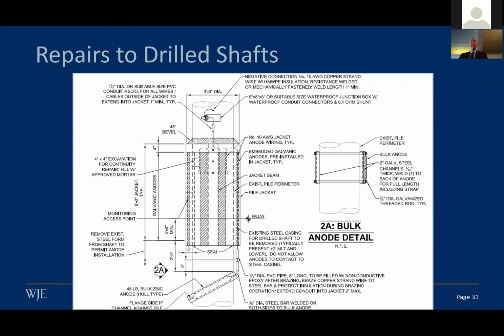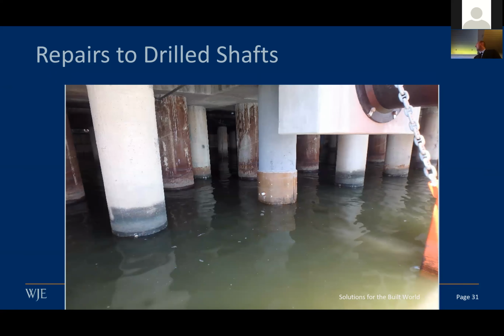Where there was more significant damage, such as those spalls that we had a couple pictures of, instead of just doing local repairs, we also wrapped the concrete with these cathodic protection jackets. These cathodic protection jackets feature a bigger bulk anode towards the bottom. And those provide the cathodic protection such that the zinc gets consumed as opposed to the corrosion occurring in the reinforcing bar. So it's a way of ensuring that you last the 50 years that you want to, and you just have to design all those features together with your repairs. And this is just an example of what that looks like. The jacket is extended 3 to 5 feet above the water just to represent that splash and tidal zone that's the most critical for the drilled shafts.